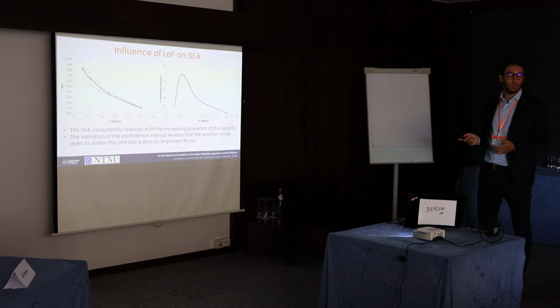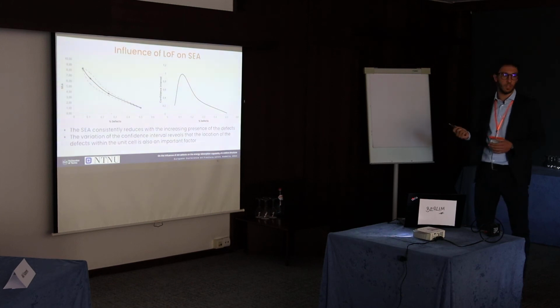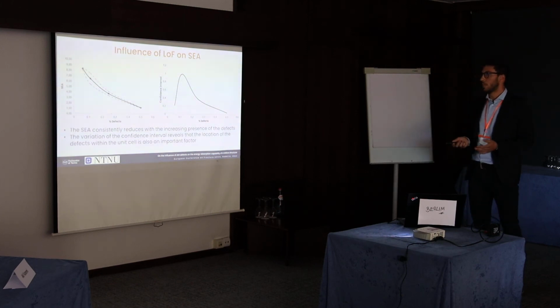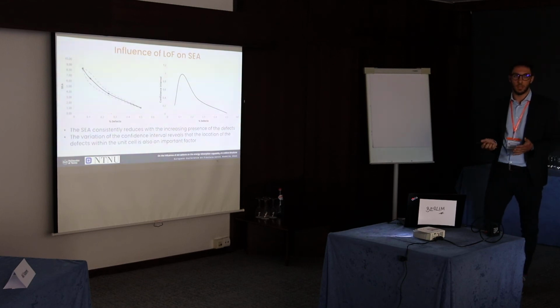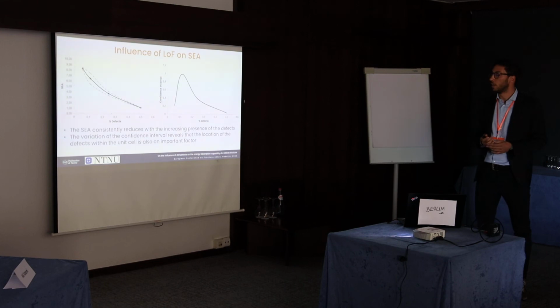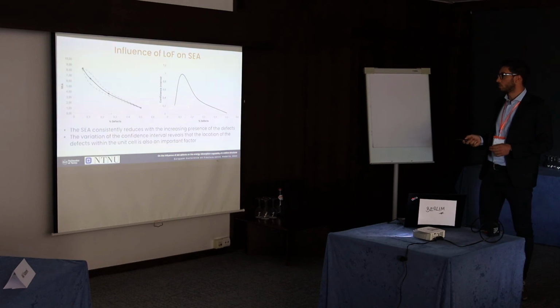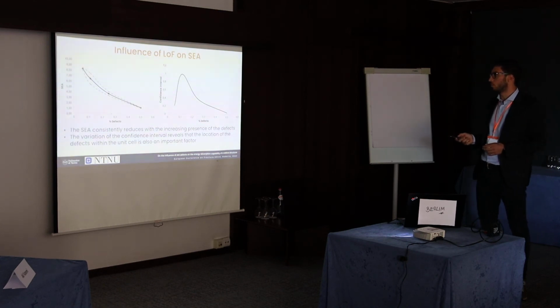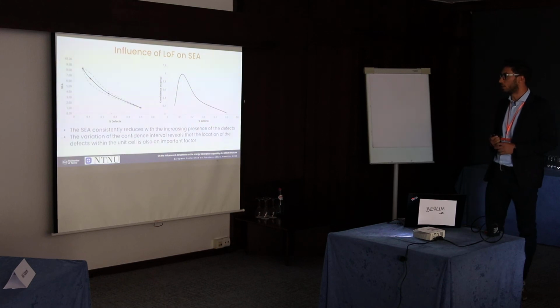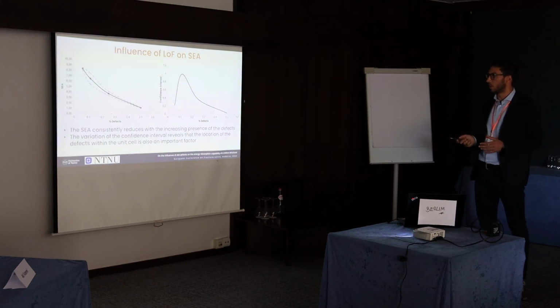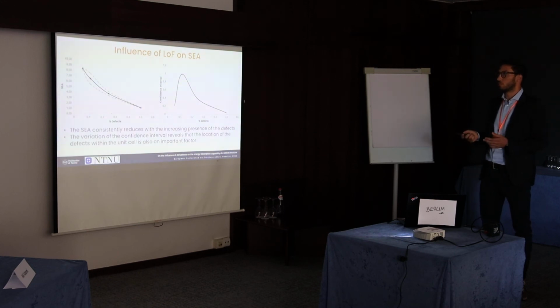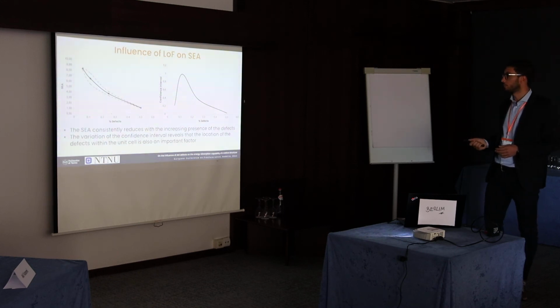And similar considerations can be made for the lack of fusion defect. Again, there is a consistent variation of the specific energy absorption with the defectivity. In this case, it was a bit more severe with respect to what we obtained with the variation of the diameter, mainly because we modeled the lack of fusion as a material that cannot absorb any energy. And similar considerations can be made on the confidence interval, which tends to decrease for the middle range of the defectivity. In this case, it decreases a bit faster because of the greater severity of this defect.